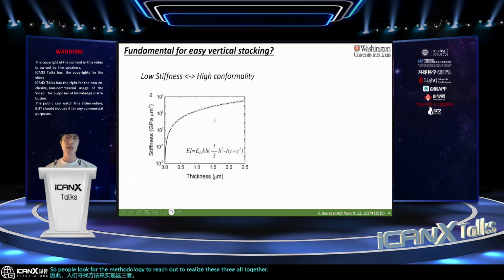And we can find the answer to how we achieve those three from this fundamental graph. As you can see, when we reduce the thickness of a device and material, it eventually leads to extremely small stiffness, so that it can be flexible and conformal as well. Also, this stiffness concept is very closely related to the required adhesion energy, which means that it is easy to make vertical stacking using very thin nanomaterial.